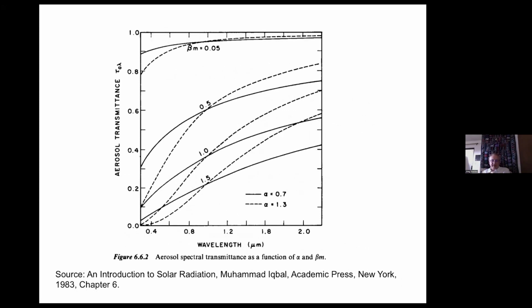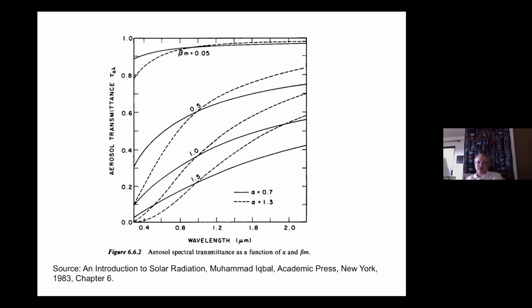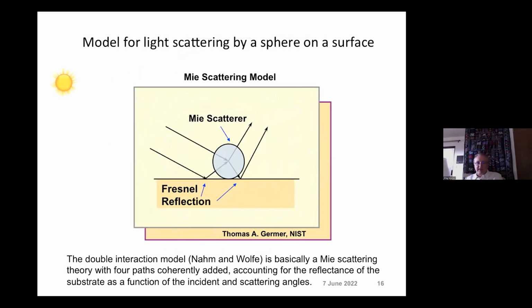All right. So with that introduction of what already exists in the book, I noticed that the shapes of the curves, this is theoretical, and again, this is from the same book by Mohammed Iqbal, Academic Press. Please look it up. We could get with different alpha values and different beta values, different shapes that have this same general aerosol transmission tau. So I recognize this shape because we measured this same type of shape when we took glass coupons, let them soil in the desert or here in San Jose, and then measured the transmission versus a clean glass. And so I said, well, if we could get the same shape for the atmospheric transmission as we get for glass coupons, let's apply this to the particles when they have deposited on a surface. They're the same particles, aren't they?